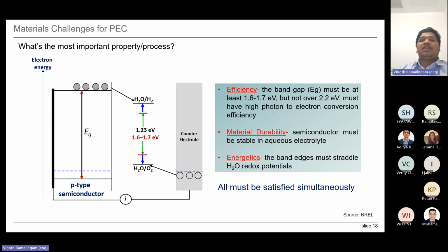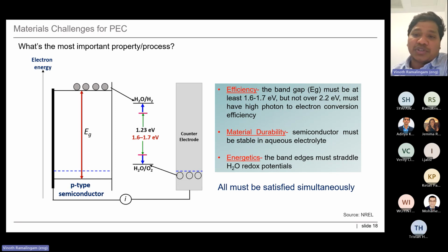So what are the material challenges in PEC systems? When we are looking for potential materials, we need to look at three important parameters. For example, the first one is the band gap. As I mentioned earlier, the band gap should be slightly higher than 1.23 electron volt so that it can promote the water splitting reaction, but it should not go over 2.2 electron volt. In that case, it starts absorbing more UV region rather than the visible region. So we need to carefully choose the material that has the right band gap to promote this reaction.